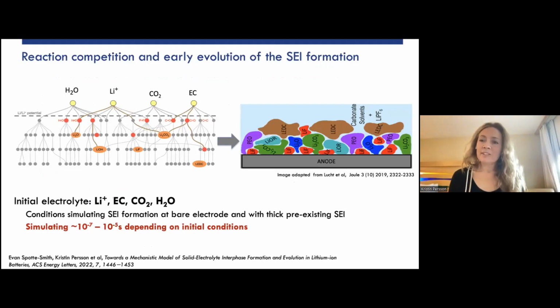Okay, so the last piece of this SEI business. Let's say that now we put together a system. In this case, it's water, lithium, and we can add impurities like carbon dioxide and ethylene carbonate, and we look at all the possible reactions that can form. We pick out the ones that we like from kinetics and thermodynamics, and we can now run kinetic Monte Carlo and look at the competition between them, and see if we can start predicting, by first principles alone, the early formation of the SEI.